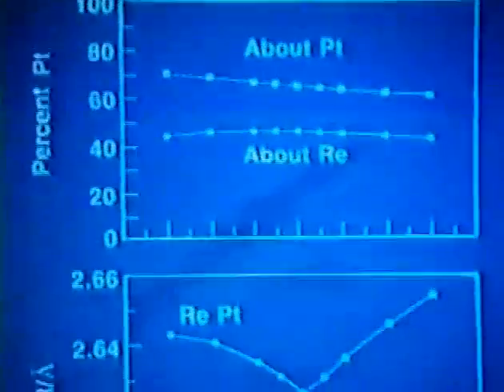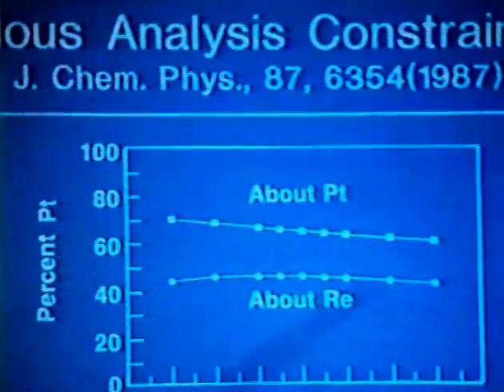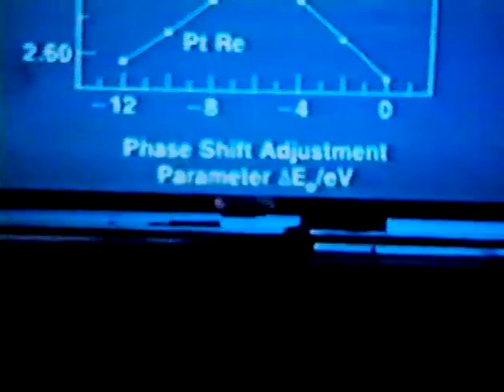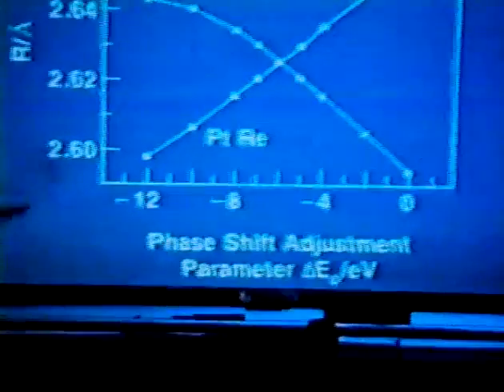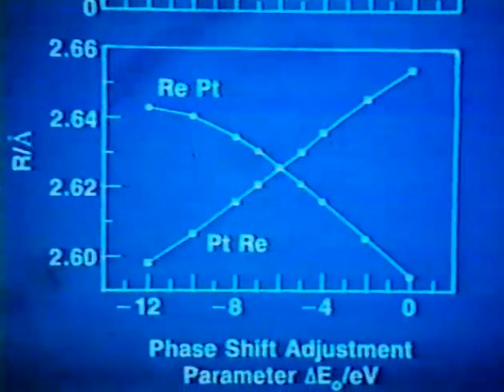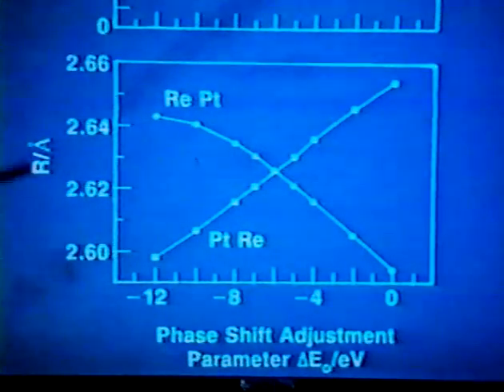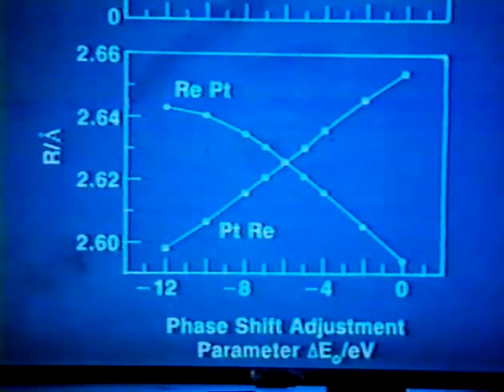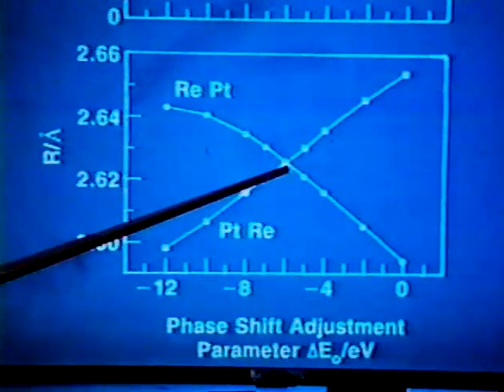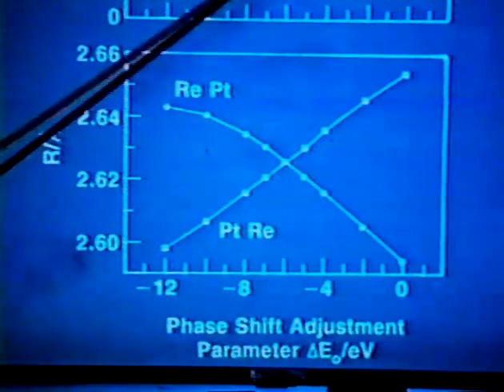We had previously, before the work that I'm describing here really, recognized that when you have spectra from two different components in a sample, you can reduce the number of variables by recognizing that there's an equivalence in the meaning of the parameters. For example, the platinum-rhenium distance is equal to the rhenium-platinum distance by necessity. What I've plotted here is distance in angstroms between platinum and rhenium, and a dummy parameter that we use to adjust the platinum-rhenium and rhenium-platinum distance from an analysis. We would repeat an analysis adjusting this dummy parameter until we'd forced the rhenium-platinum distance to equal the platinum-rhenium distance. Some other variables that we were also able to determine, such as the composition of the first rhenium coordination shell, were mildly dependent on this parameter down here.